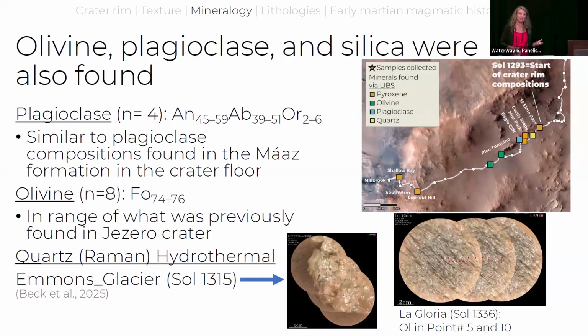We also found some olivine, only 8 of them, which was quite surprising. It might be just because we might not have targeted the right targets, but we have found 8 olivine with forsterite between 74 and 76. It's relatively primitive. It's not extraordinarily primitive, but it is. And they represent compositions that were also found throughout the whole traverse.